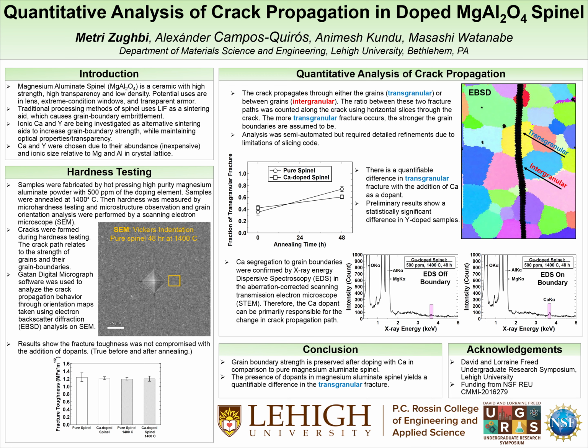This gives us an idea of how strong our fabricated samples are, and also, since ceramics undergo brittle fracture, causes 4 cracks to propagate from each tip of the diamond. Part of that crack is outlined by the little yellow box, and that's what I'm most interested in. As you can see in the bar graph on the left, results show that doped calcium brings no detrimental effects to mechanical properties of spinel samples, and although it isn't shown here, yttrium-doped samples share similar results.